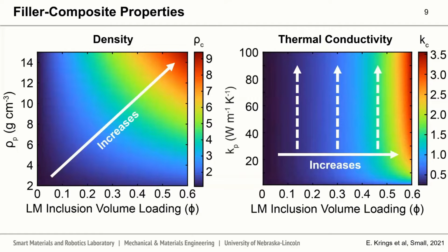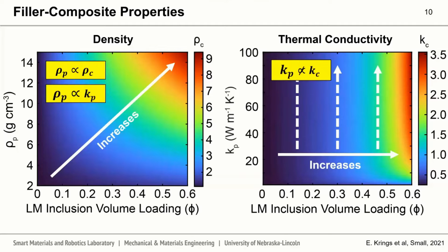So to conclude this, we see that the density of the particle filler is proportional to the density of the composite, which is as expected. We also know that the density of the particle filler is proportional to the thermal conductivity of that particle filler. But counterintuitively, the thermal conductivity of the particle filler is not proportional to the thermal conductivity of the composite and remains nearly constant above some level.